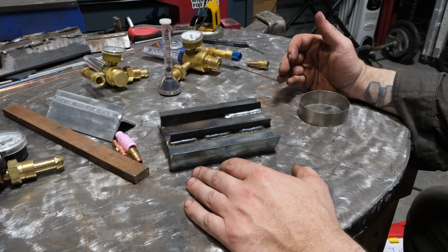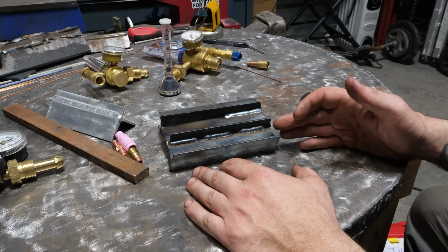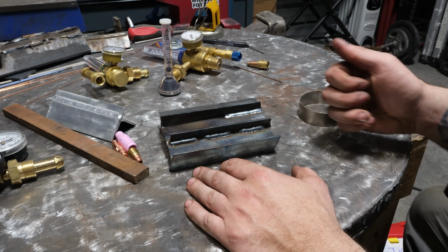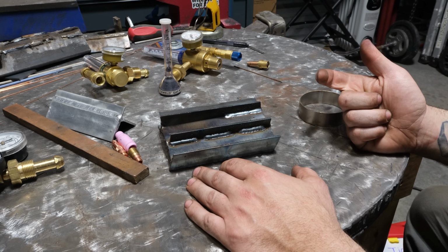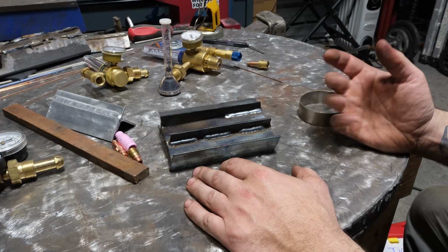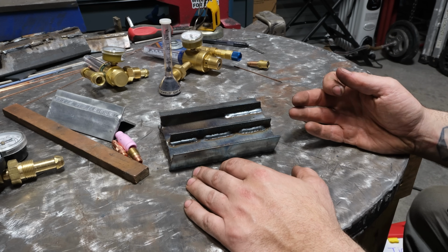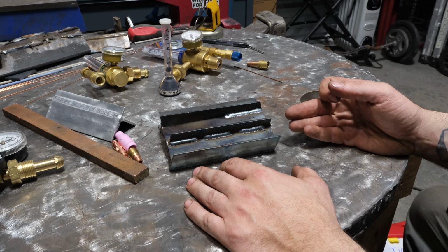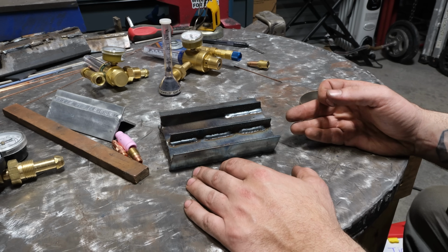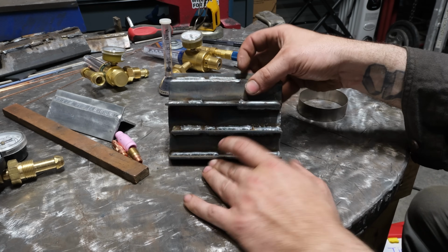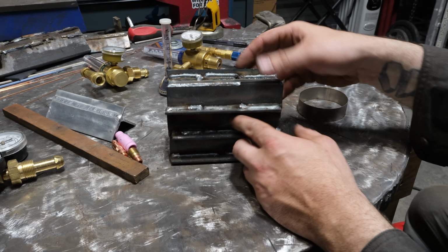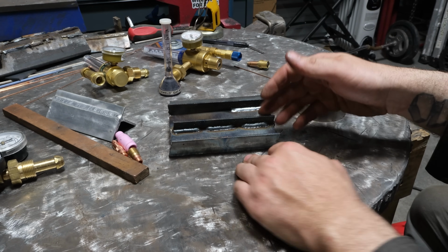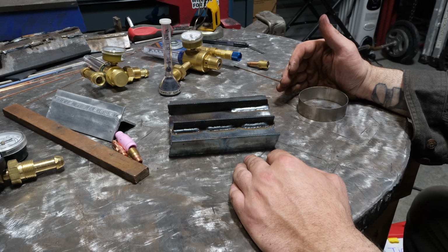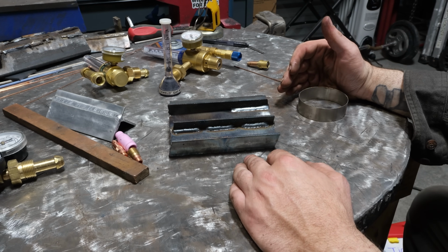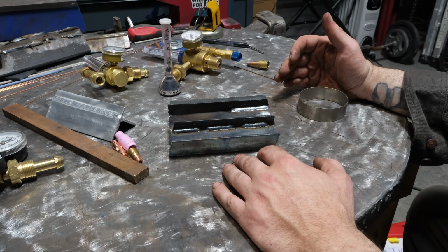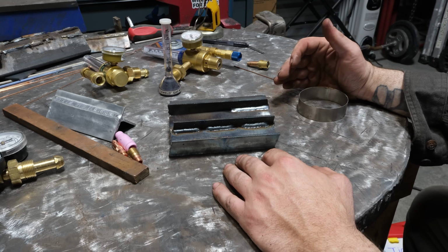But the truth is that you have to go by what you're seeing for defects. So if you see porosity, if you see discoloration, anything like that, or if you notice at the start of a weld, it doesn't fuse very well and it sputters. If you see excessive spatter, like here where there's a ton of spatter, and that's kind of a bad example, but excessive spatter could also be an indication of gas shielding problems. And if you see that, bump your cubic feet up a little bit.